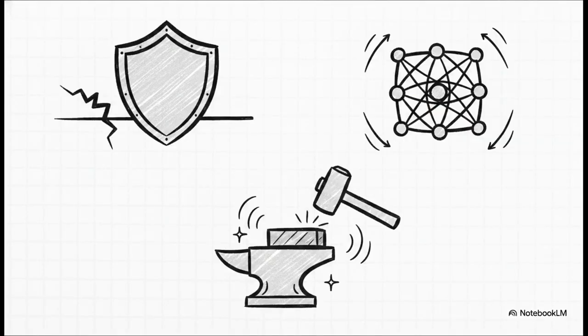So wrapping up the material science side of things, the key takeaways are crystal clear. Number 1, surface hardness is what prevents those initial microscopic extrusions. Number 2, crystal structures with high internal resistance, like ferrite, are inherently better at fighting fatigue than the softer, more spacious structures like austenite. And number 3, specifically tempered structures like sorbite or troostite vastly outperform standard structures like pearlite. Why? Because they perfectly combine toughness with that absolutely crucial resistance to atomic sliding.